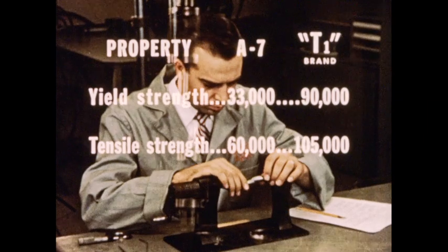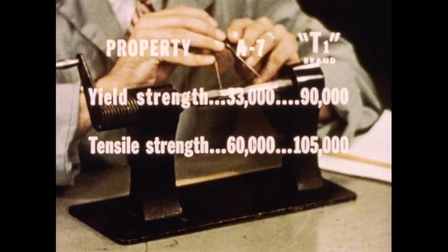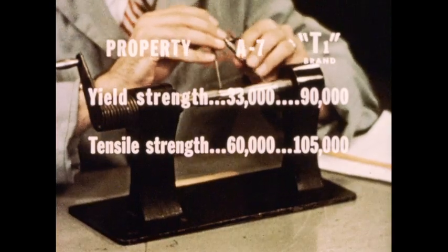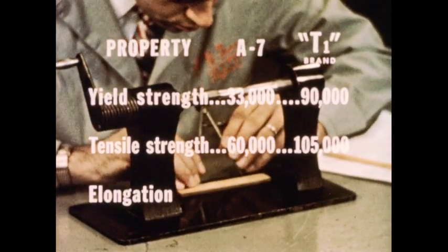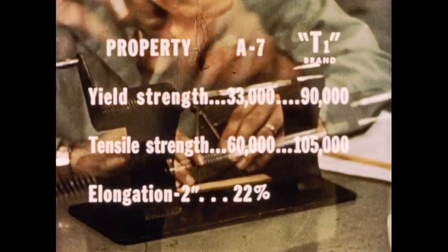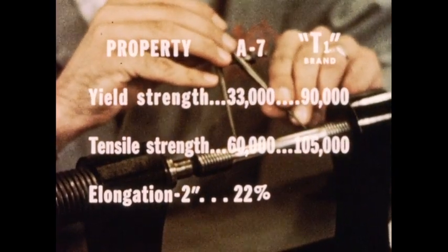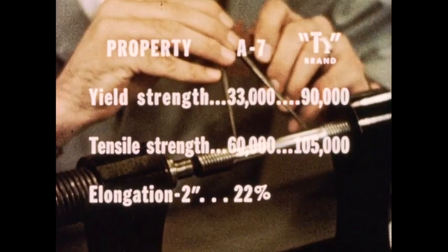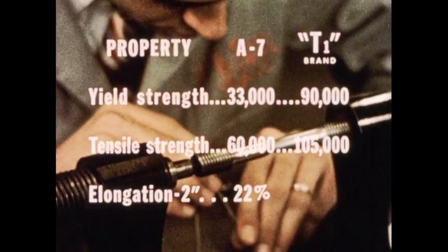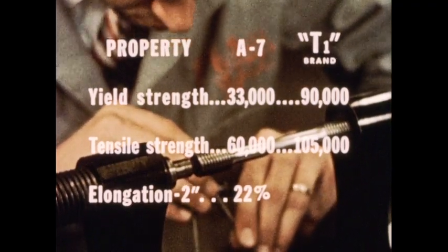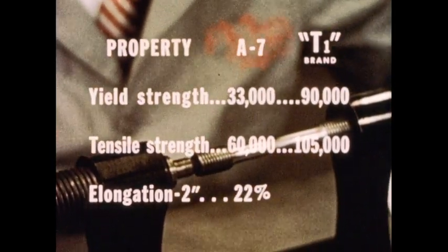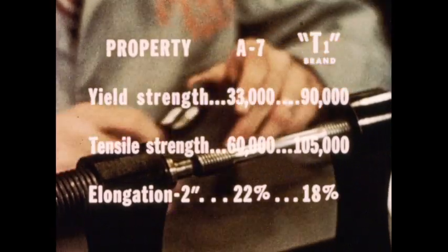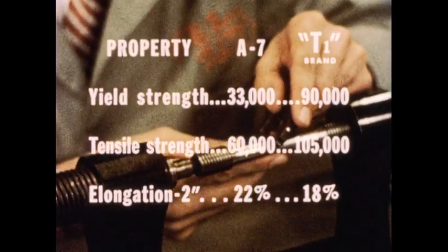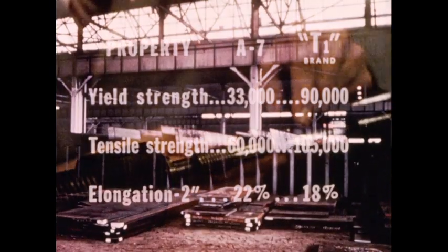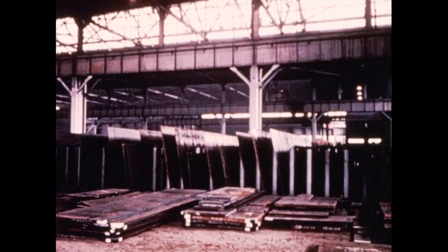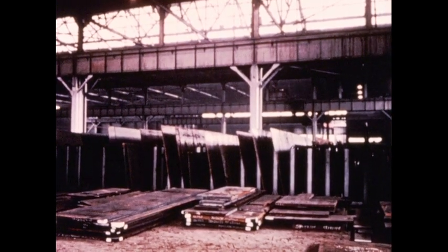Next, a wonderful reversal of form. It is expected that a carbon steel like A7 will have excellent elongation, and it does, 22% for a 2-inch length. But the very properties needed to create a tensile strength over 105,000 psi are expected to cut down elongation. Yet, T1 is completely different. In a 2-inch length, its elongation is 18%, very close to conventional steels. Yes, here is a unique steel, ready for an exceptionally wide range of uses.